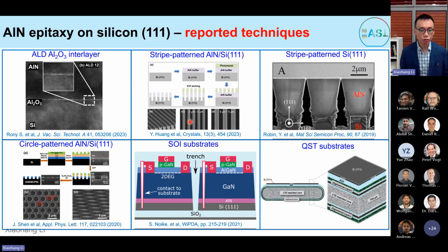So how do you address the strain? How do you manage the strain, right? In the past, a lot of the studies have relied on patterned substrates. You either pattern the silicon, or you grow an aluminum nitride buffer and you pattern the aluminum nitride, right? All of those technologies have been effective to different degrees, but the process itself is complex and costly. So our work primarily wants to focus on how to get crack-free, high-quality aluminum nitride on planar silicon. Okay, so how do we do it on planar silicon?